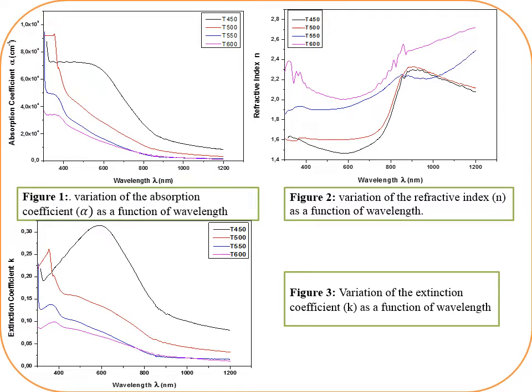This indicates that there is an increase in the densification of our films, maybe due to increase in thickness. For wavelengths above 800 nanometer, we notice that the refractive index of samples at T450 and T500 decreases, while it continues to increase for samples at T550 and T600. In Figure 3, the extinction